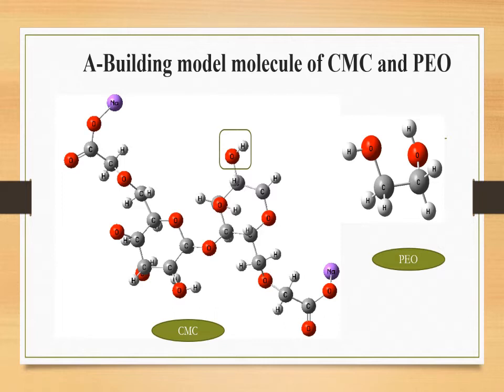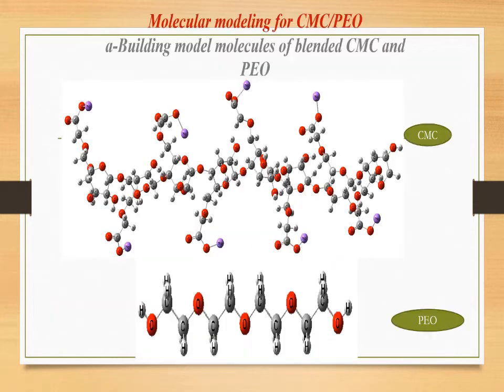As we see, the CMC structure contains a large number of hydroxyl groups, which are among the most reactive functional groups present, through which CMC can interact with PEO and form hydrogen bonding. Building model molecules of blended CMC and PEO. As the shape and size of polymers play a very important role in their electronic properties, CMC was blended with PEO in different blending ratios: trimer CMC with monomer PEO, dimer CMC with dimer PEO, and monomer CMC with trimer PEO. We suppose that we have 4 units of CMC and 4 units of PEO in order to follow the same sequence presented in the first presentation in the experimental part.